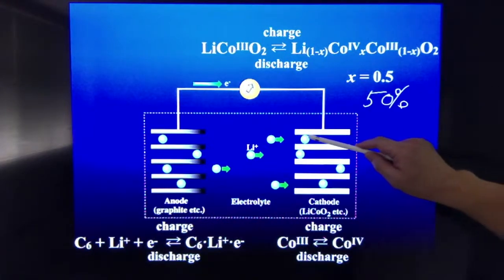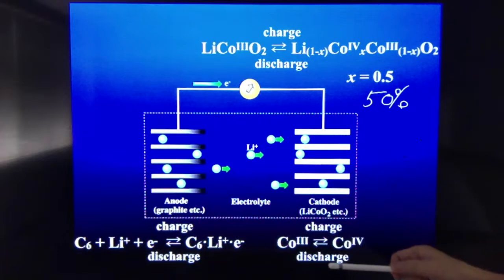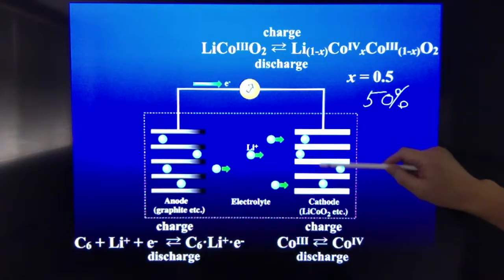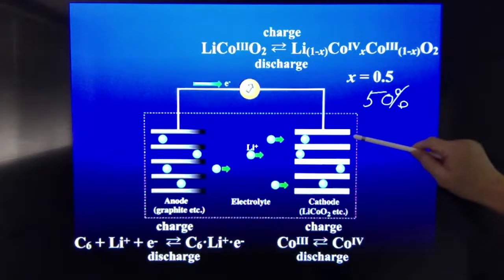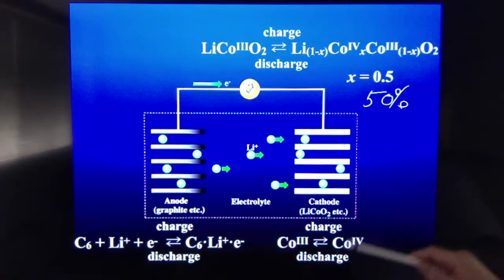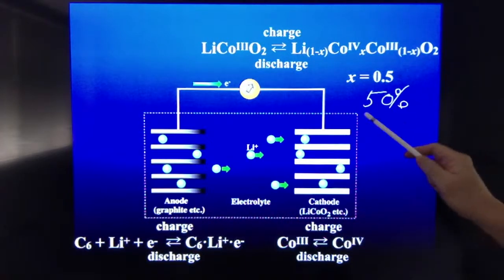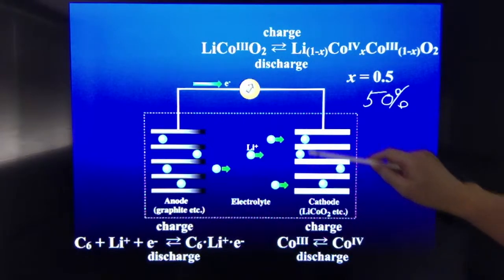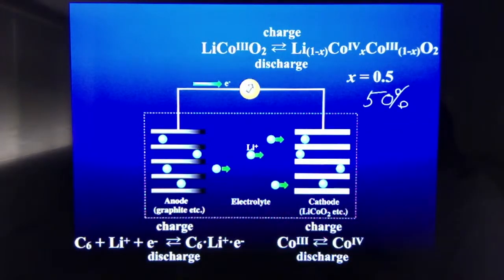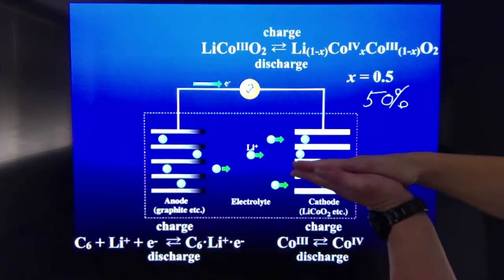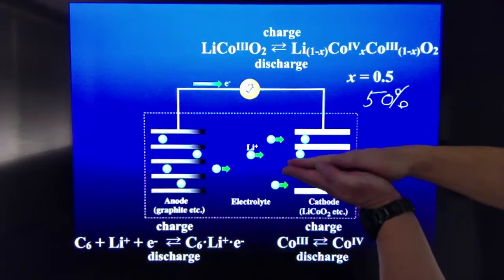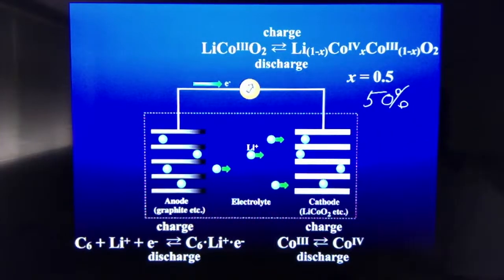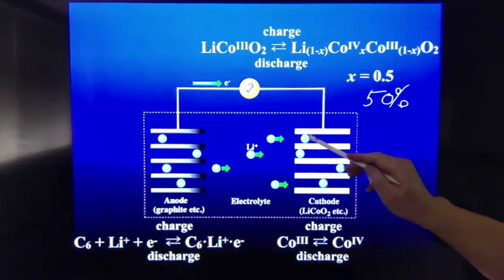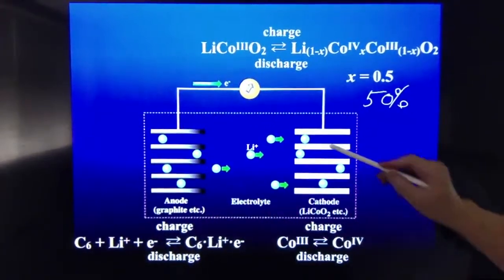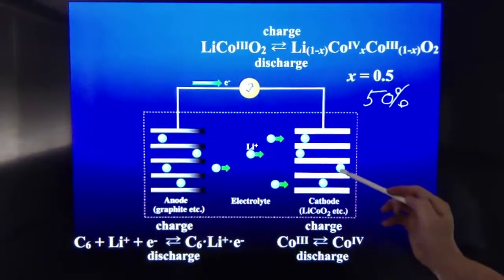And 50% cobalt you can use. Because these lithium ions are not just staying here, but also function as columns of the layer structure. If you use almost all the lithium ions completely, you get some empty cobalt oxide here, and the layer structure collapses. You can never get this layered structure again. So no more equilibrium. So you can only use 50%, and you leave some lithium ions here as columns and keep this structure. And then the reaction is in equilibrium.